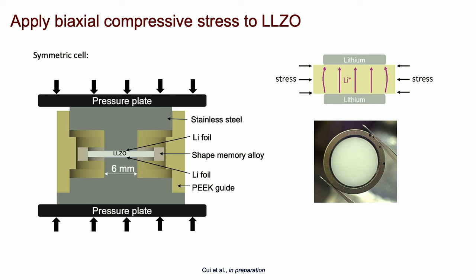He built this symmetric cell where we have LLZO in the middle, sandwiched by lithium, and what he did was use a shape memory ring. This is a device we bought online. It's used for pipe fitting. It's like a washer, and when you heat it up, it closes and tightens up, and then it's never going to release again unless you bring it to very cold temperatures. Anyways, it applies a stress on the LLZO.